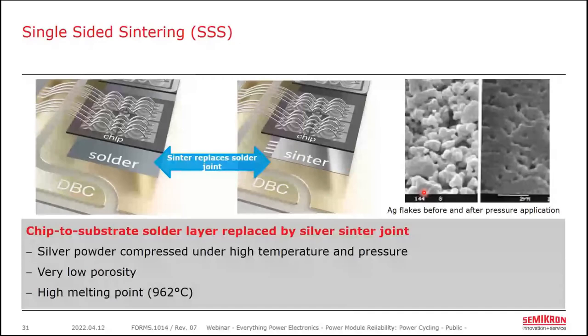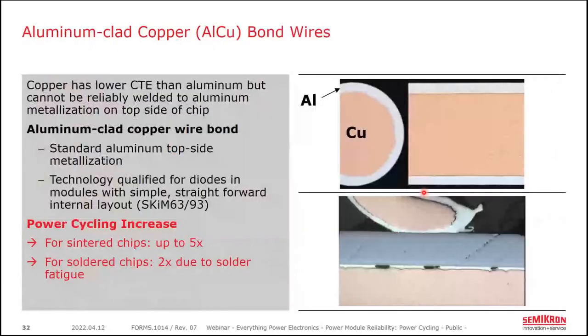The other weak point we discussed is the aluminum bond wire. One method is to change the aluminum to a material with a lower coefficient of thermal expansion, such as copper. Thus you would have less stress on the bond wire joint with each heating and cooling cycle because the bond wire is expanding less.